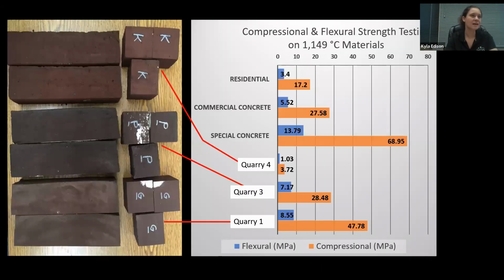So when we put these things to the test, we did compressional and flexural strength testing, and you can see just from the data that Quarry 1 compressionally was comparable or did a little bit better than your commercial concretes, whereas the Quarry 4 material did really, really poorly. And so we needed to figure out why that was, because the processes to sinter all of these things were the same. Grain size was about the same, temperature was about the same, all of that was about the same, but we were getting different results. And I'll continue with that in just a second.